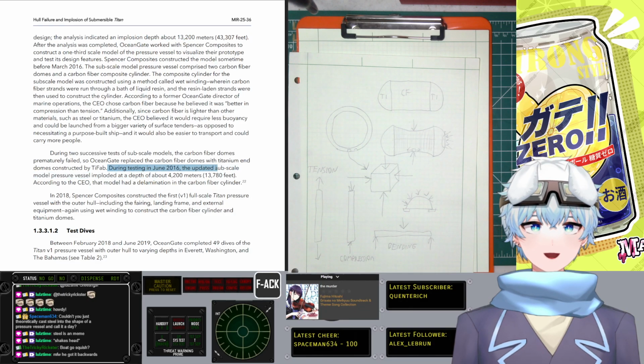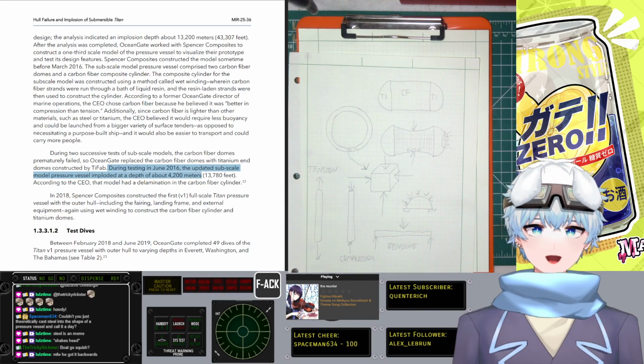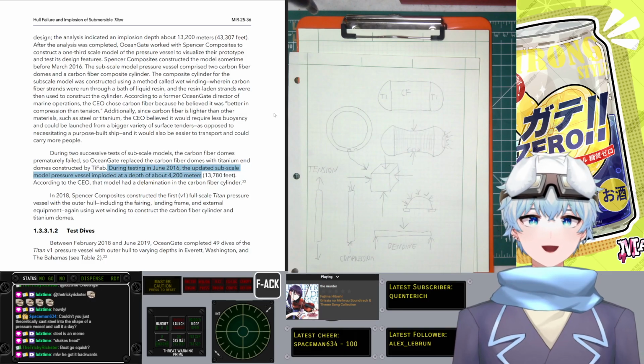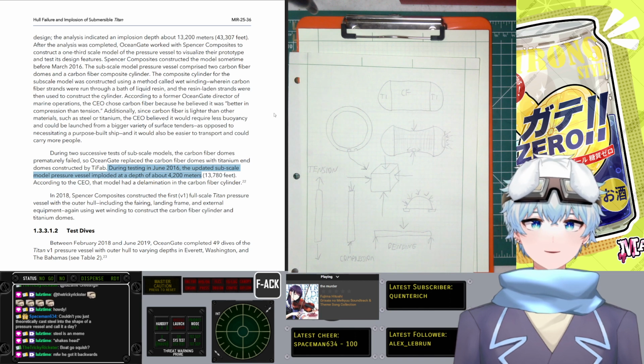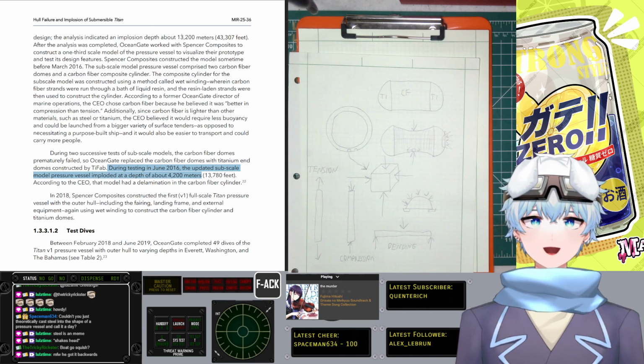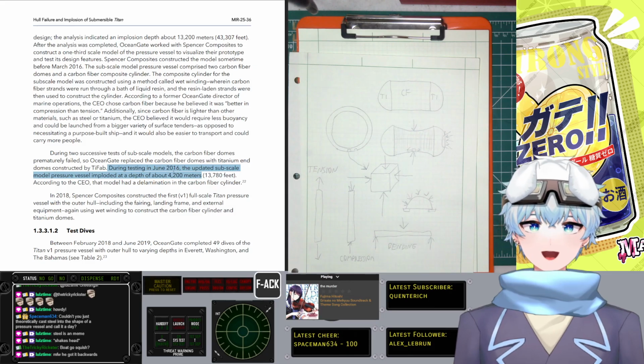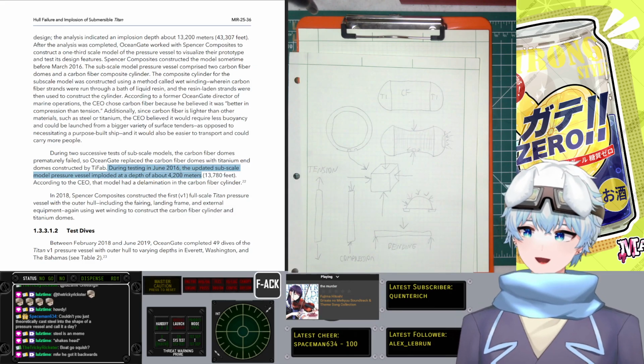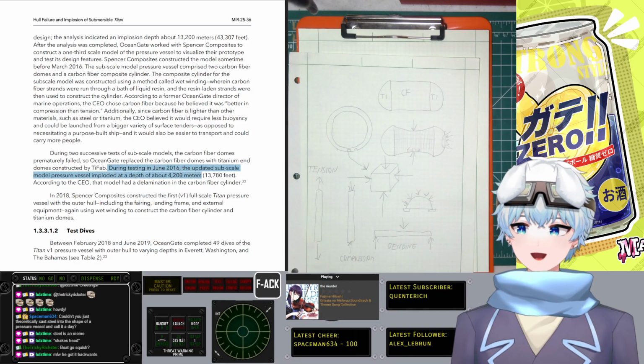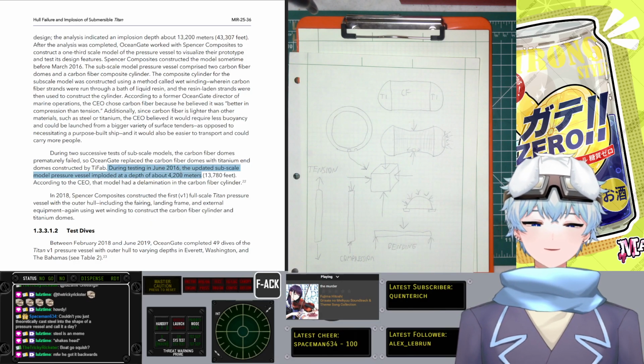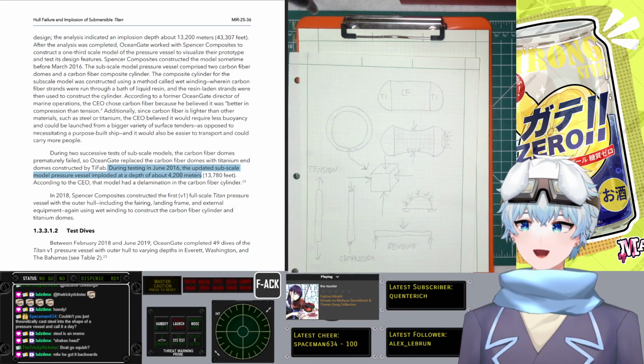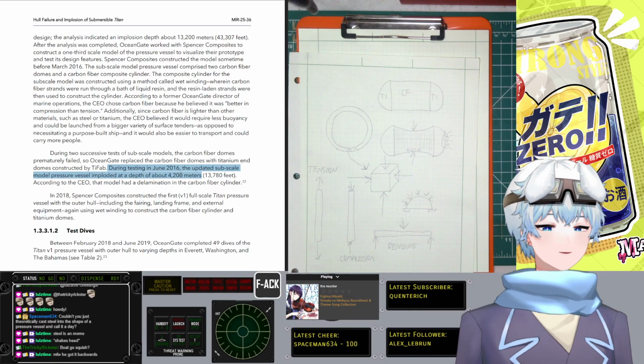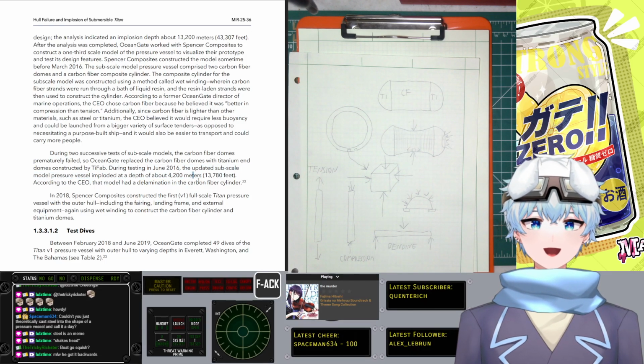During testing, the updated subscale model pressure vessel imploded at a depth of 4,200 meters. There is some ambiguity here that I would like. It would be nice to have a little bit more information on if this analysis is only for the full scale or if the subscale one is also supposed to last that long. It is unknown. But at the very least, we know that the subscale one was tested down to a depth below what the actual submarine is supposed to go to, which gives you a little bit of a safety factor, which is important.